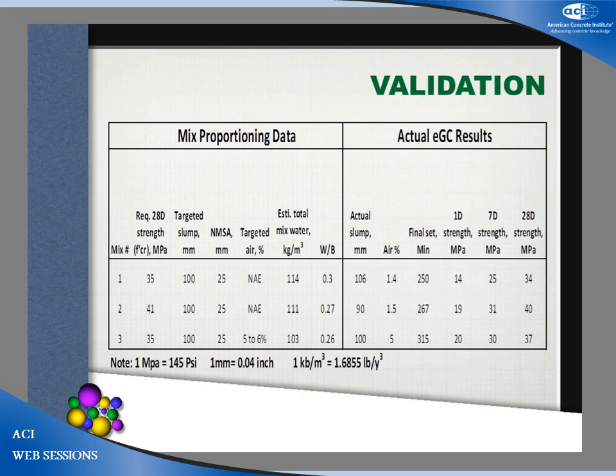Now, we validated this mix design method with three mixes. Mix number one, we already saw in the sample computation. That one had the target 35 MPa required compressive strength, 100 mm slump, that is 4 inch. And we actually got in the lab mix 106 mm slump and 34 MPa strength. It's very close.